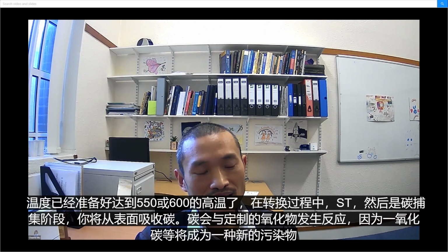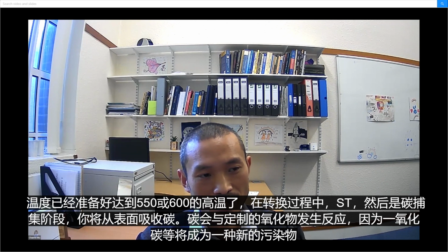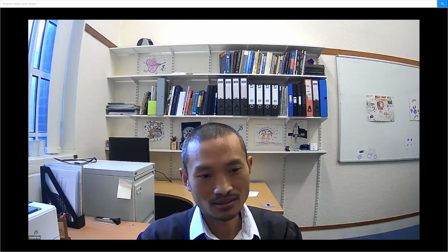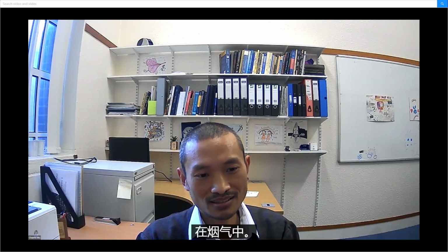But especially for the reverse water gas shift reaction, if you have nickel calcium oxide, the temperature is relatively high, 550 or 600, and you're going to have carbon formed on the surface during the CO2 conversion stage. And then in the carbon capture stage, the carbon will react with calcium oxide and become carbon monoxide, and that will become a new pollutant in the flue gas.